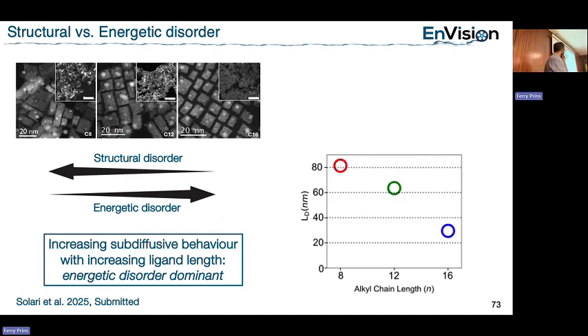So this again is the diffusion length in nanometers. These 8 carbon atoms go about 80 nanometers, whereas the 16 only go 30 nanometers.